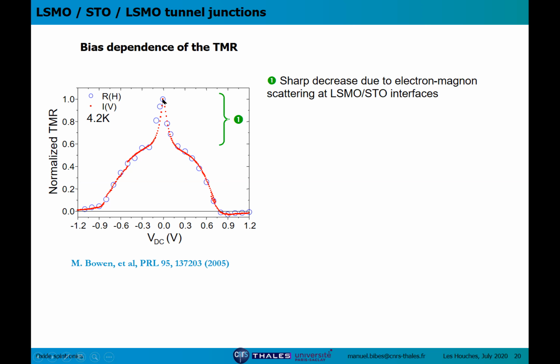There's the first regime where the TMR decreases quite sharply, and this occurs over maybe 100, 150 millivolts. This is believed to be due to electron-magnon scattering, or excitation of magnons by the tunneling electrons. And this usually is associated with a flip of the spins of the tunneling electrons. So this effectively reduces the spin polarization of the tunneling electrons, and the TMR as a result decreases as well. Eventually, if you increase the bias voltage further, you reach some kind of kink or plateau, and then the TMR keeps on decreasing again.